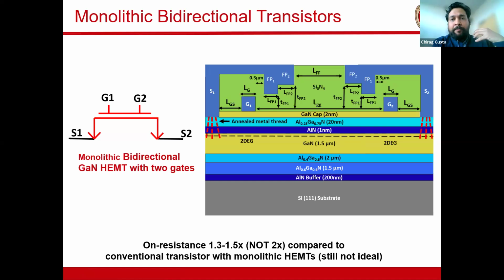But beyond those advantages, there is some inherent advantage that you can get from lateral transistors if you make a monolithic transistor: instead of getting that penalty of 2 times the resistance, the penalty you are going to get is a little bit less. So for example, if you have a 600 volt, 10 ohm conventional transistor, maybe you can get away with a 600 volt, 15 ohm part instead of a 20 ohm part. So this to me was very exciting.